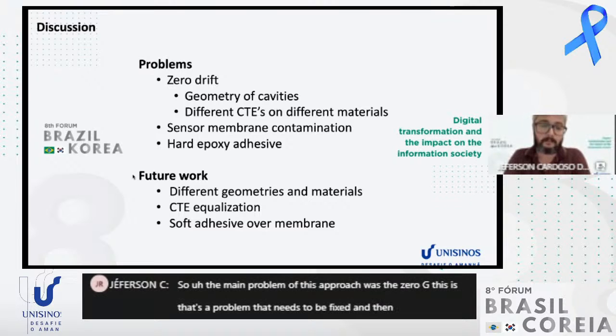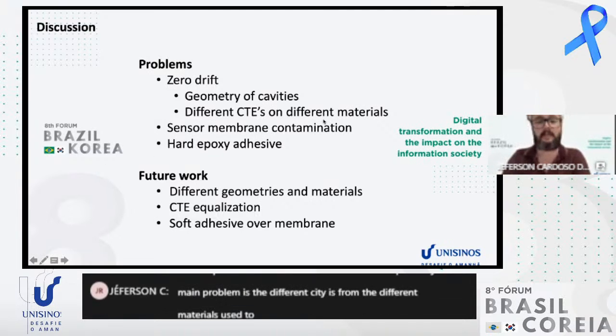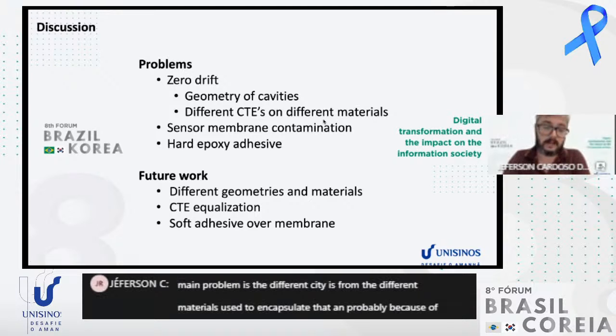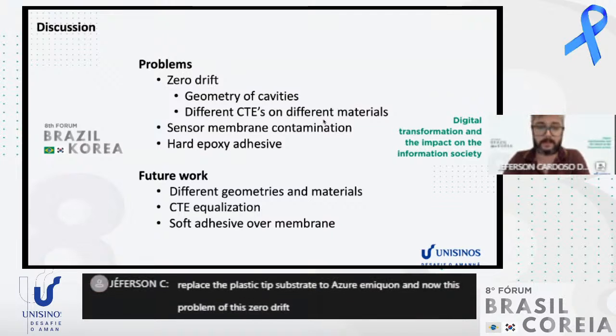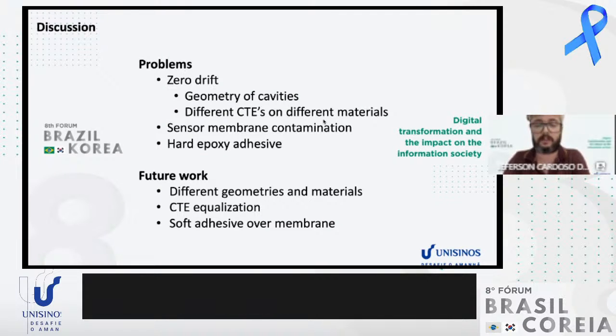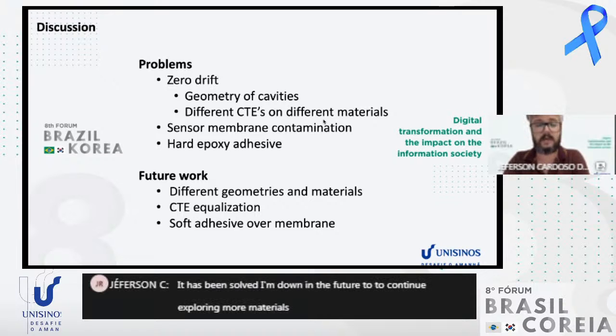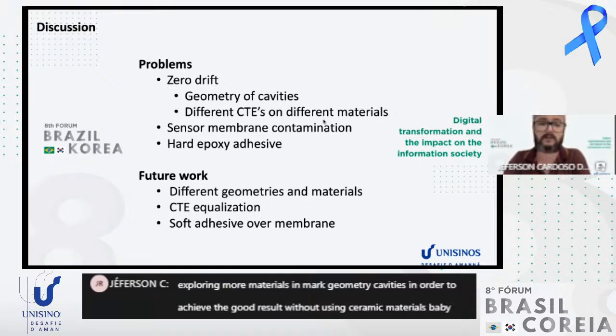And then probably the main problem is the different CTEs from the different materials used to encapsulate that, and probably because of the plastic. I have assembled some new versions of this product. The data is not shown in this presentation, but I replaced the plastic tip substrate with a ceramic one. And now this problem of the zero drift has been solved. I intend in the future to continue exploring more materials and more geometric cavities in order to achieve good results without using ceramic materials. Maybe it will be possible to achieve good results using plastic materials.